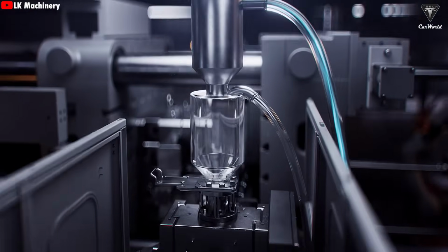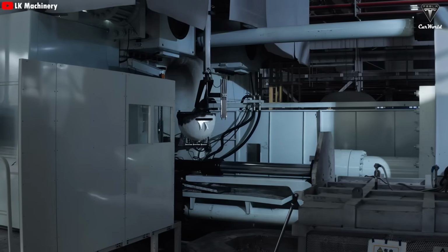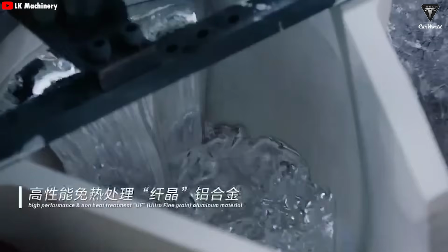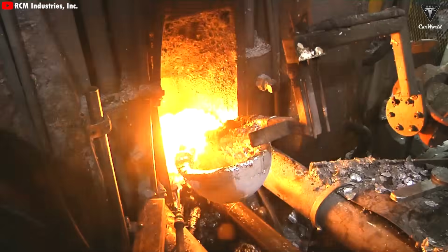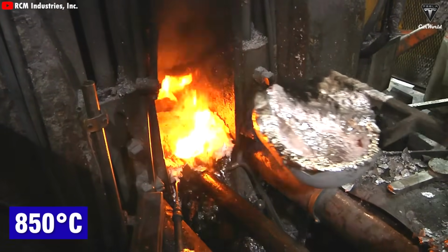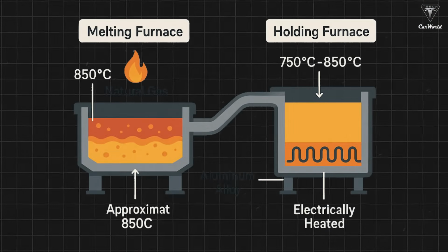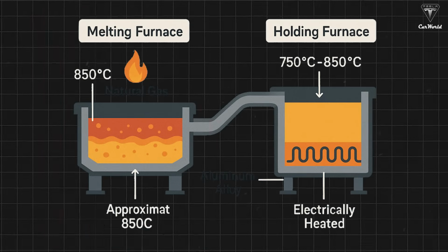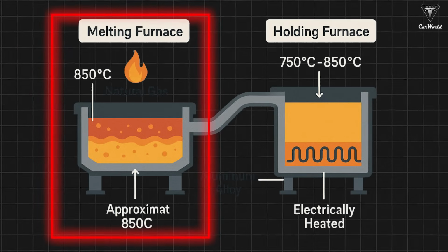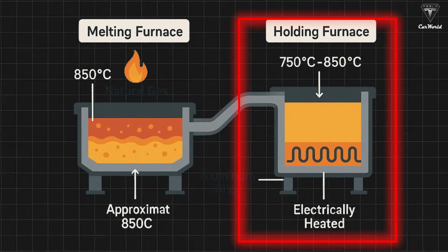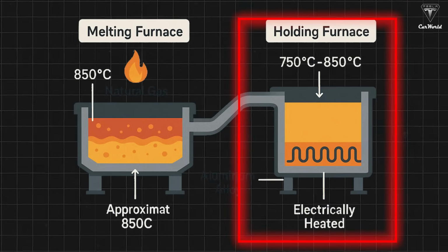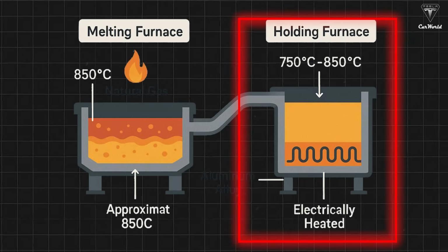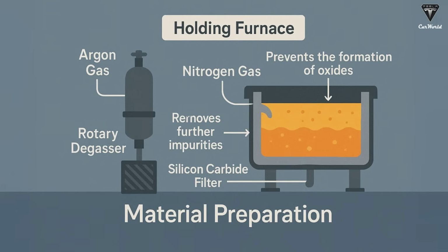But here's the thing, even with all that power, the basic way it operates isn't too different from the 16,000-ton version. First, the process still begins with material preparation. Tesla melts down new aluminum ingots along with the leftover aluminum from previous casting cycles in a furnace heated to around 850 degrees Celsius. As far as we know, the Giga Press uses a two-furnace system to handle the aluminum alloy. One furnace, used for melting, is gas-fired and runs at about 850 degrees Celsius. The other holds the already molten metal and is electrically heated, keeping the temperature between 750 degrees Celsius and 850 degrees Celsius. The empty space inside the holding furnace is filled with nitrogen gas, which prevents oxidation in the molten aluminum and helps maintain a stable temperature.